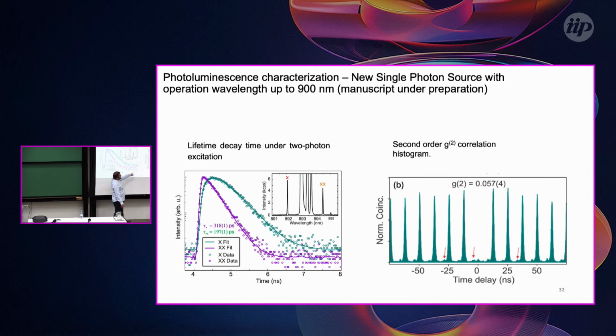And here is also a correlation measurement that we did to prove that this was a single photon source. If you compare this value, it is very small, but it's much bigger than for the gallium arsenide quantum dots. But this is because we don't have the correct setup for measuring this wavelength, and you see that we still have a laser coming from the excitation. This means that we can very easily improve this G2 value.